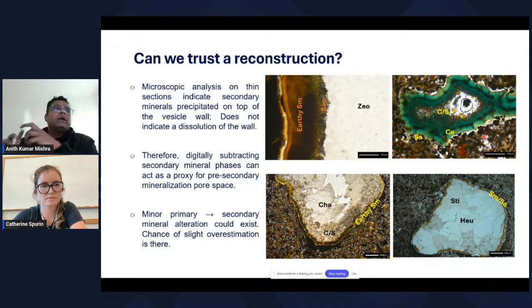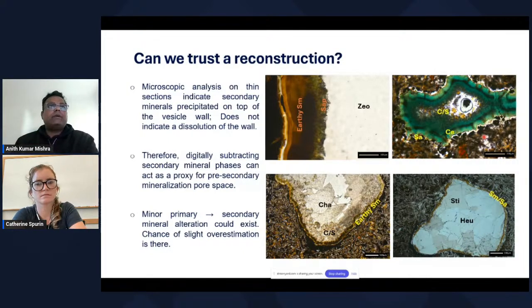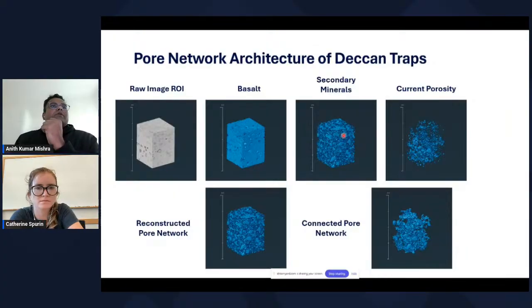And therefore, if we can digitally subtract the secondary mineral phases from the 3D volumetrically rendered CT scan images, we can probably reconstruct the pre-secondary mineralization porosity. This is not the primary porosity I'm talking about. This is strictly the pre-secondary mineralization porosity, what was there before this secondary mineralization actually happened. We did that. Initially with this sample, we saw this is the current state of porosity, and we found no connectivity in this particular sample, which we showed a few slides back.